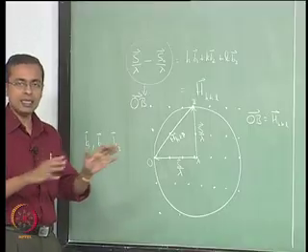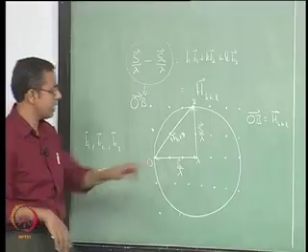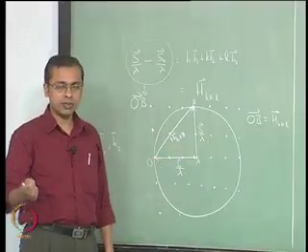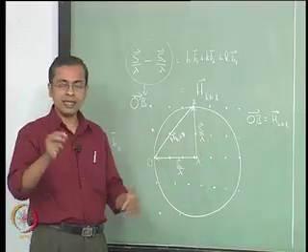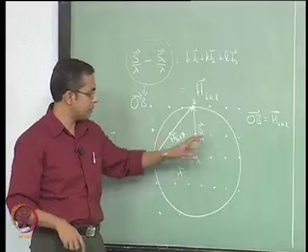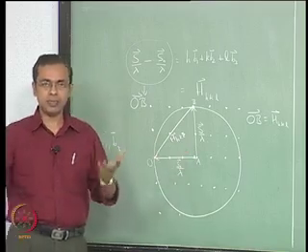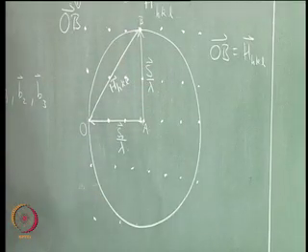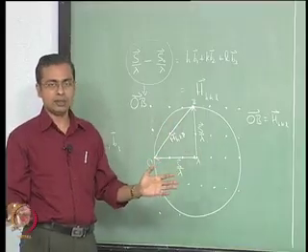So wherever you actually end up as a valid integer sum of B1, B2 and B3, it will get you to one of these points, they are valid reciprocal lattice points. Anywhere in the middle it will not be an integer sum of B1, B2 and B3, it will be some fractional sum that will get you to in-between locations where there is no valid reciprocal lattice point, but it is still reciprocal space, fine. So this circle that we have drawn is a circle drawn in reciprocal space, okay.